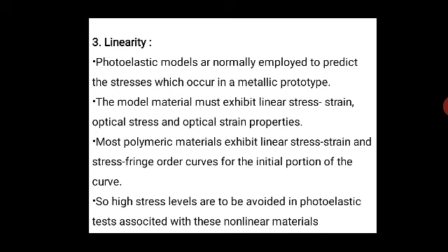And for few data analysis which are available in the optical strain relationship, however, since the photoelasticity method is usually employed to determine the stress differences, typically stress-strain curves and fringe orders can be determined. And one thing is that at higher levels of stresses the material may exhibit non-linearity effects. For this reason the higher stress levels are to be avoided in photoelasticity tests which are associated with these non-linear materials.